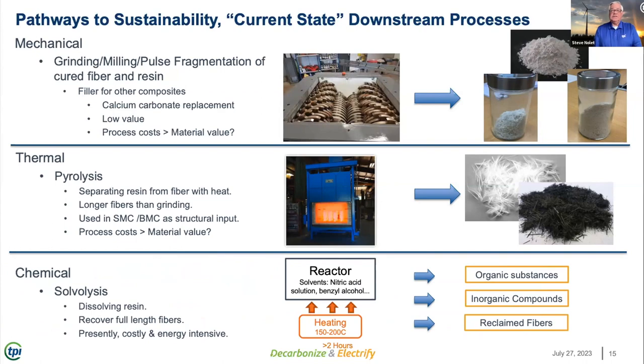result in. The challenge, of course, is these are high energy input through heating of very caustic solvents, nitric acid, benzyl alcohols, not particularly environmentally friendly solvents either, resulting in organic substances, inorganic compounds, and reclaimed fibers. Typically the pathways. We've seen recently some hybrid processes where a chemical solvolysis is done before a pyrolysis, which reduces the energy required in pyrolysis and less fiber degradation. So we're seeing some blurring of the lines as well. But I would suggest that these are the primary pathways that today have been demonstrated at industrial level.